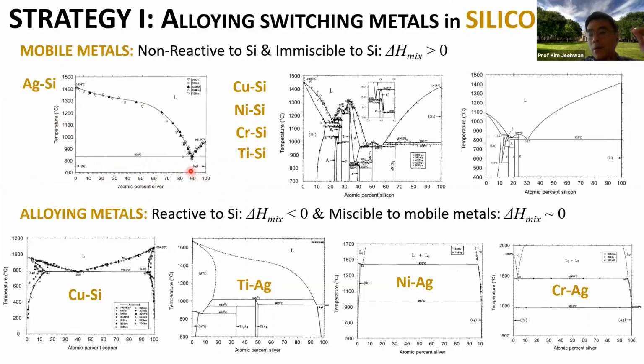like each other. The perfect material for that was silver, because as you can see from this phase diagram, silver has no solid solubility in silicon, and silicon does not have solid solubility in silver, meaning that silver attachment to silicon is very weak. That way, silver can freely move around to form the filament, to be a skinnier filament, to be a thickened filament. So for that sense, all this copper, nickel, chrome, titanium are not good mobile metals, because they will form a silicide, a line compound. So we cannot use this.